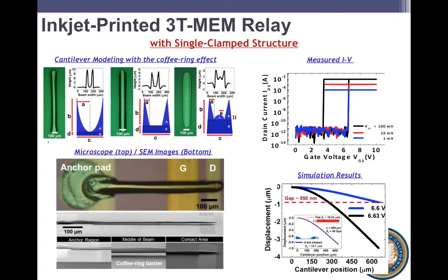So what we want is a relatively stiff cantilever. But it turns out the switching voltage also depends on the stiffness of the cantilever. So we want something that's very well controlled. And it turns out we've sort of found an interesting way to do it. So I told you earlier that the coffee ring effect causes these ridges, which are bad for normal devices. But we really like the ridges here because it allows us to make a U-shaped beam for free.